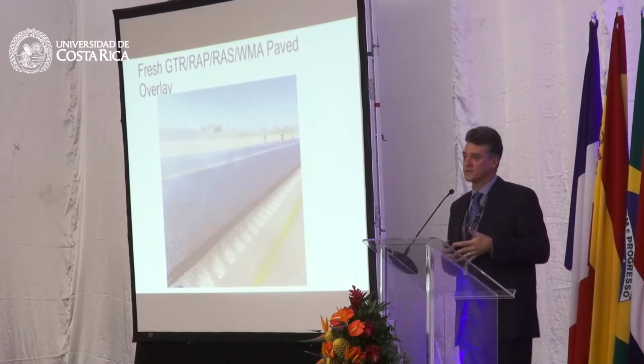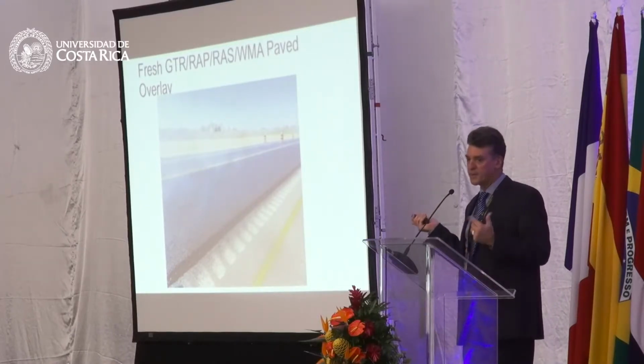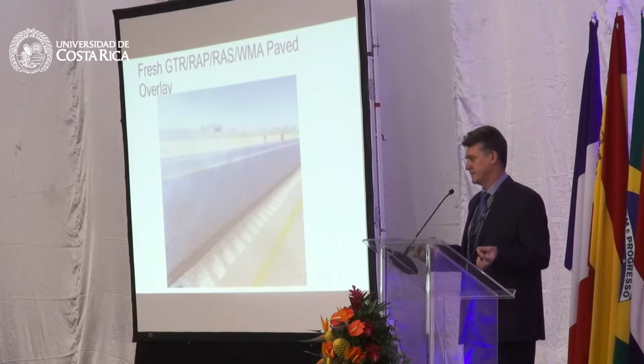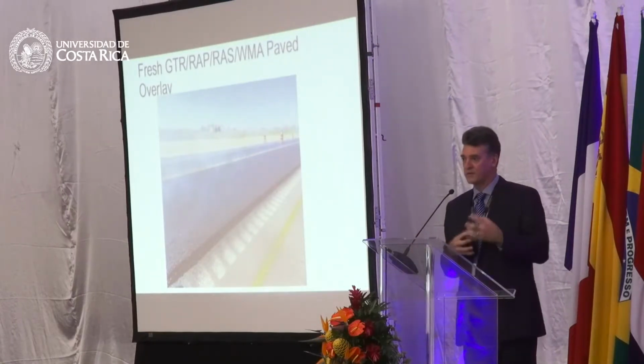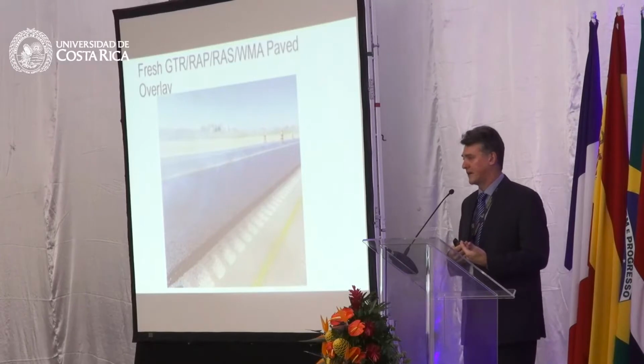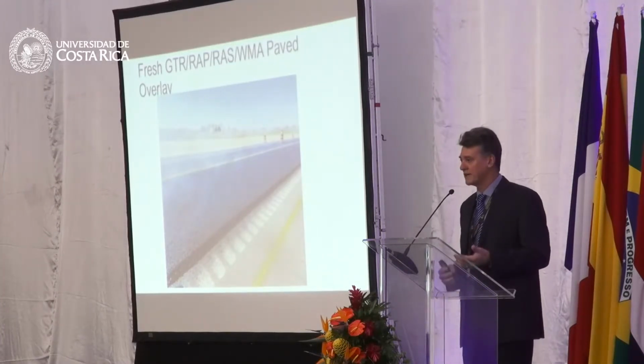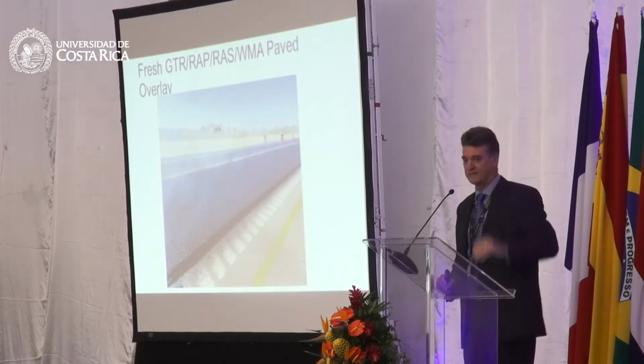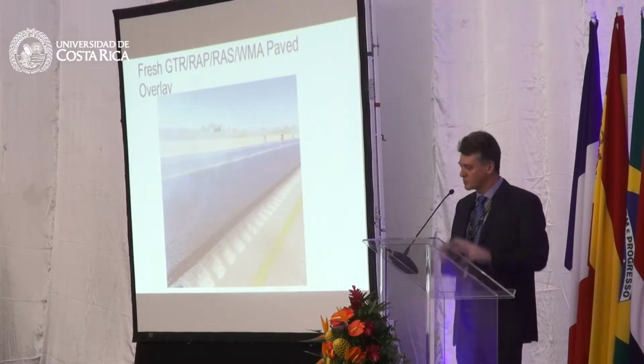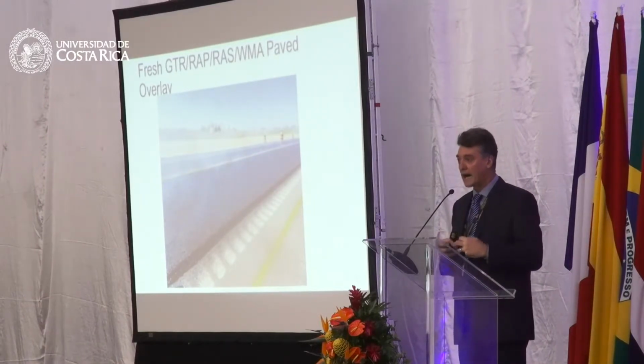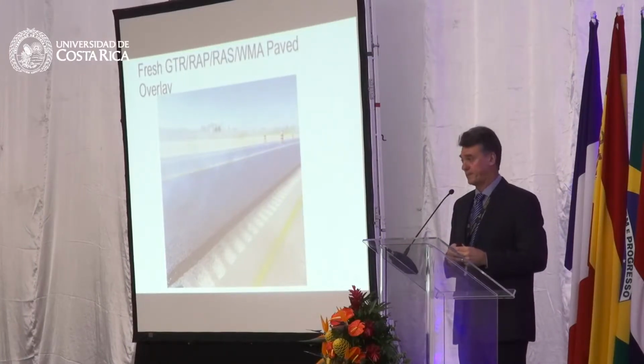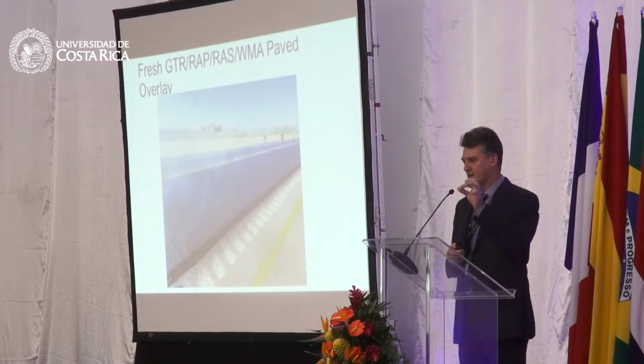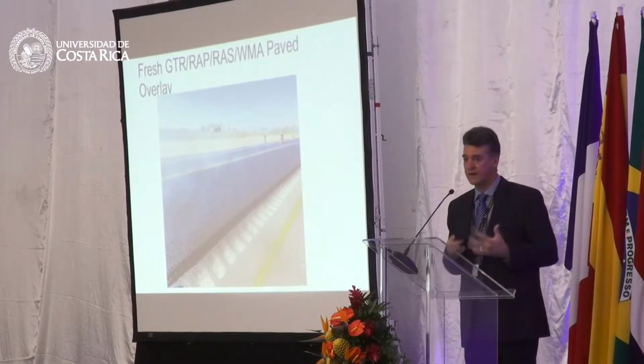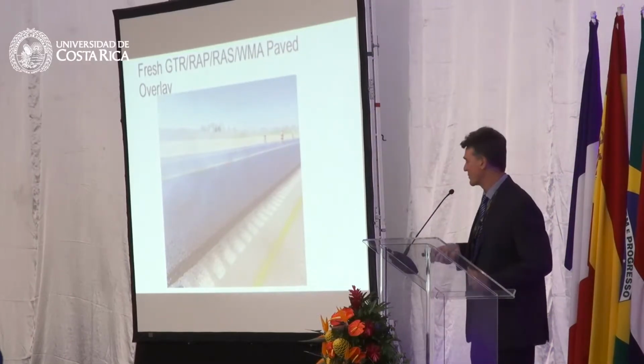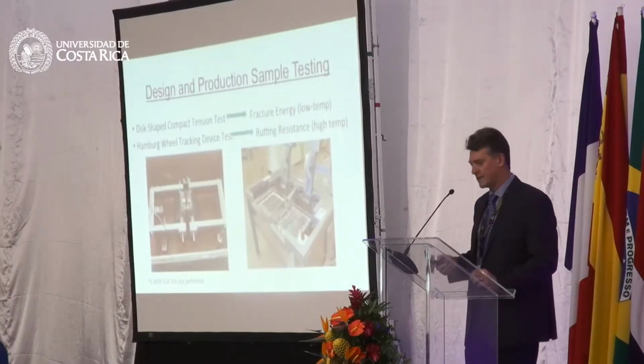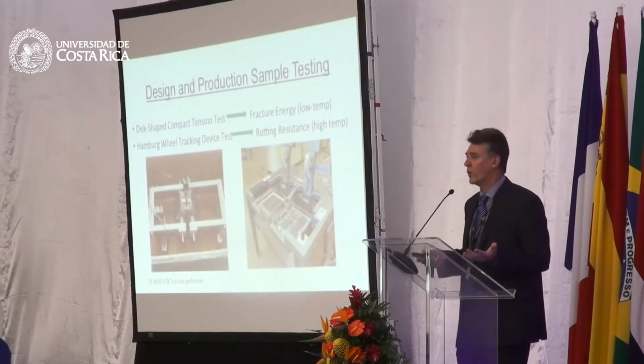It's a real challenge to try to characterize these mixtures purely with the liquid binder test, because the way all these things go together in the field, they don't completely mix. I will tell you that the roofing shingles are so stiff, their melting point is higher than the temperature of production. So those roofing shingles are partially melting. I think the same thing is true of the wrap. Not all of that wrap binder is melting and mixing. So we have a very composite material, especially when you add the rubber. And these mixture tests give us a very good feel of how it all went together.